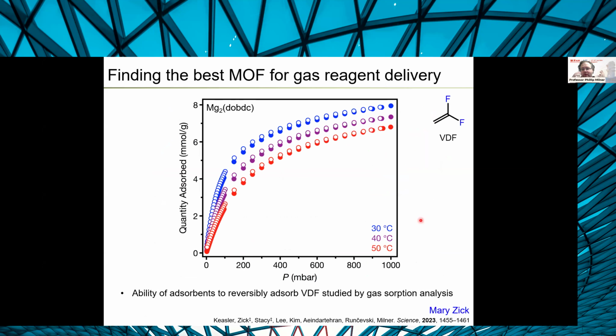So when we tried to figure out what was the best MOF to bind these types of fluorinated gases, which hadn't really been explored, Mary started by measuring uptake of this gas, vinylidene fluoride, in metal organic frameworks. To do that, we measure what are called gas adsorption isotherms. Probably almost all of you have run one of these before, if at least a surface area analysis, where we look at varying the pressure here and the uptake of the gas, with adsorption in closed circles and desorption in open circles. And so by looking at a bunch of different materials, Mary was able to benchmark their ability to bind vinylidene fluoride.